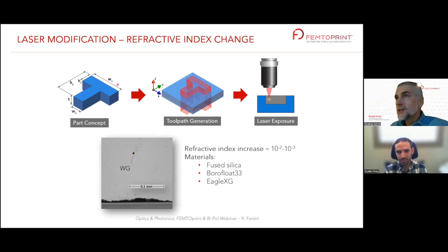How? Again, the first part is the same, but as I told you, we can focus the laser into the bulk, and we can use different processes through triggering two-photon absorption. One of the processes can be glass densification. So what we can do locally, we can densify the glass, which means we can increase the refractive index. The delta N is typically in the order of 10 to the minus 2, 10 to the minus 3. So you see here, for example, a spot where locally the refractive index has been increased. If you think about writing this on a stripe, what you're doing is writing a waveguide in the bulk of the glass.